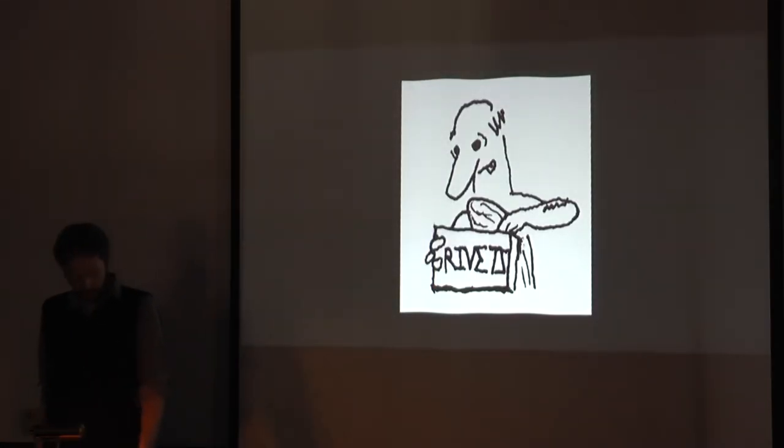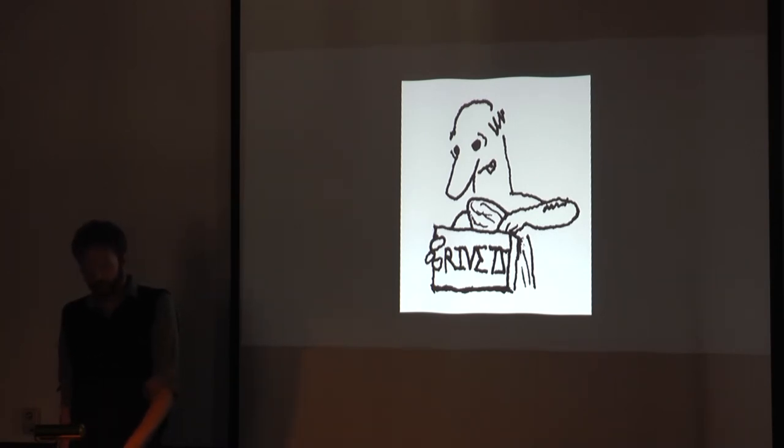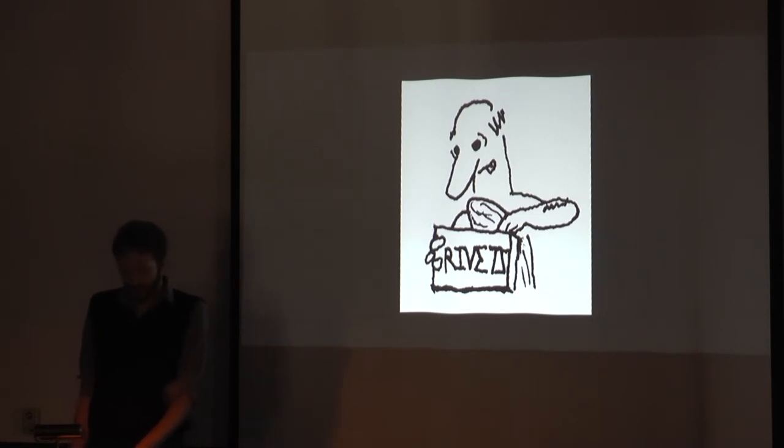To sum up, this study offers two important conclusions about ancient Greek metalsmithing and ancient Greek military technology. First, the chemical diversity of the helmet's body, its rivets, and its patch suggests that every piece was forged at different times from different recipes. This means that metalsmiths probably kept a large number of pre-made rivets around their workshops, which they could use in any of their projects. This in turn speaks to the relative sophistication of the metalsmiths themselves and gives ancient rivets a sort of one-size-fits-all quality.